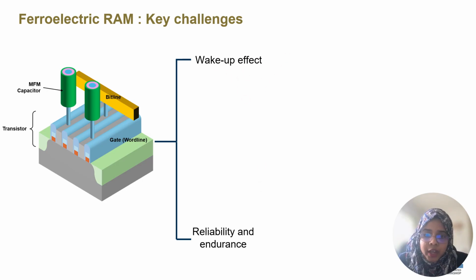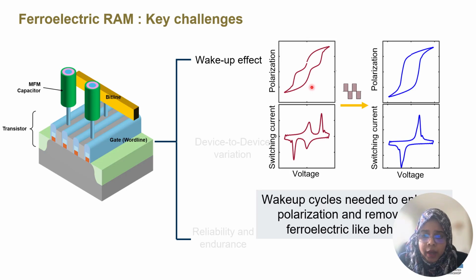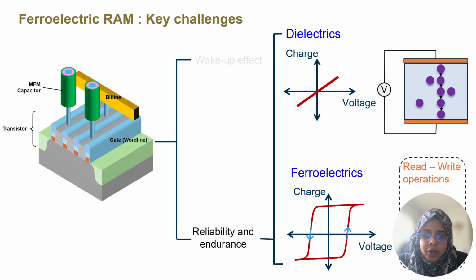For example, one of the challenges is the wake-up effect, where at the beginning we don't get enough polarization in our ferroelectric films, but we have to apply a certain number of cycles to get a better polarization value and a proper ferroelectric switching current. Another challenge is reliability and endurance. In ferroelectrics, the material goes through both the bipolar switching and also the bipolar stress. That's why the endurance and reliability of our ferroelectric materials is worse compared to conventional dielectrics, where only stress plays a role.